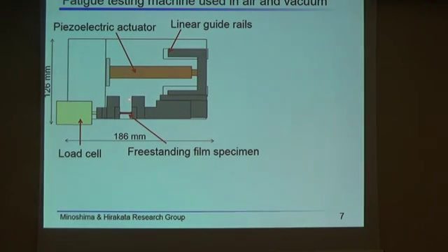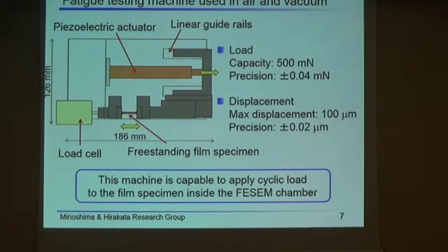Cyclic load was applied to the freestanding film specimen by transferring the displacement of the piezoelectric actuator to the specimen jig attached to the linear guide rails, as shown like this. And this is the specification of this machine. This machine is capable of applying cyclic load to the film specimen inside the FESEM chamber.